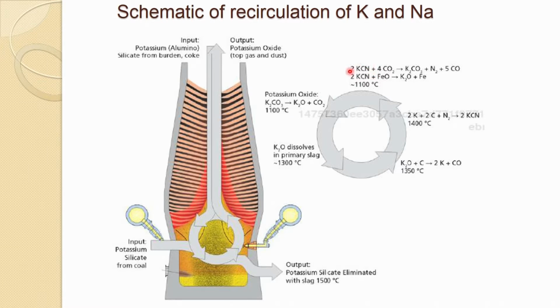And sometimes, because nitrogen is always there, it can form cyanide, and that cyanide again reacts with the CO2 in this region, in the stack region, and goes back to K2O, into K2CO3 and then to K2O. So, naturally, one way of reducing it is to have a central gas flow, so that from the center it can go out to the top gases. Peripheral flow will attack the bricks, and then there is more scaffolding, promoted in that way.